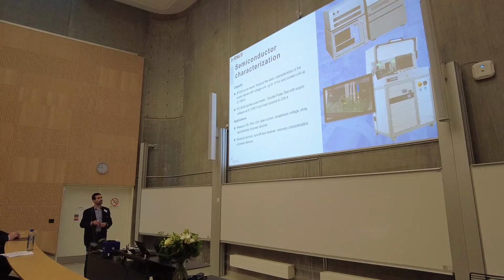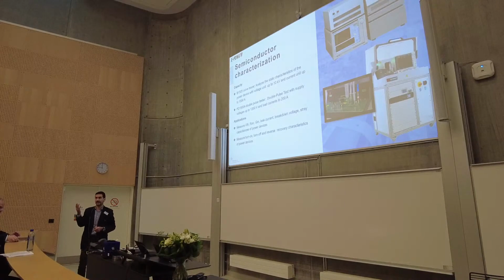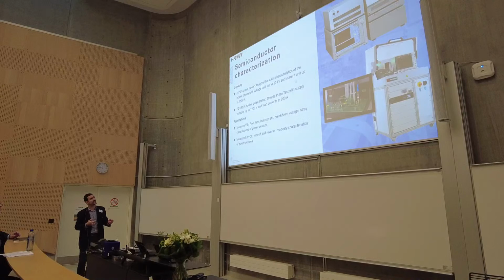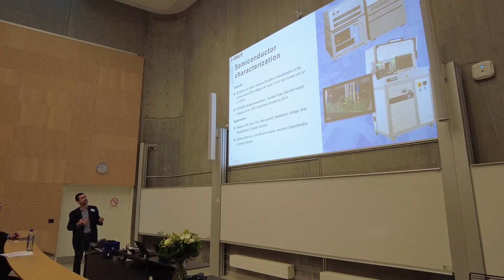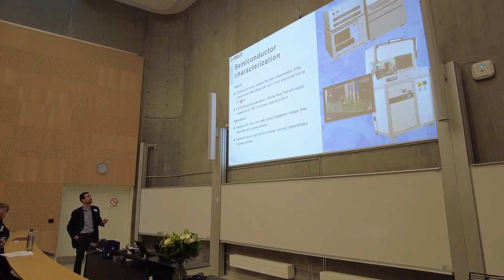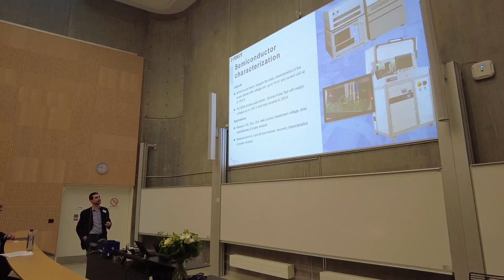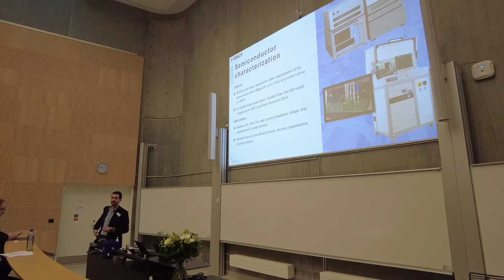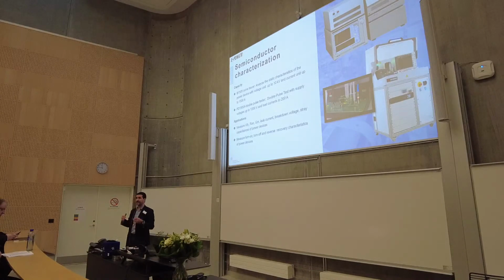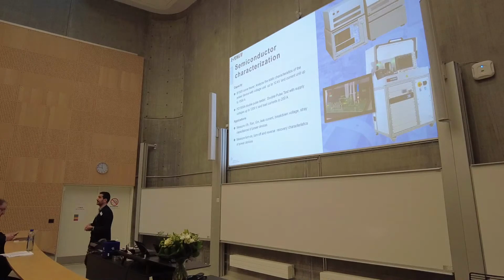And one of the last things I would like to introduce is semiconductor characterization, both from a static point of view. Many of you know this kind of equipment, which we have acquired in-house, up to 10 kilovolts and 1500 amperes capacity, but also this other equipment, which is a little bit more rare, still from Keysight, where we are able to execute double pulse testing with very, very low inductance levels, which is typically needed for testing gallium nitride components.